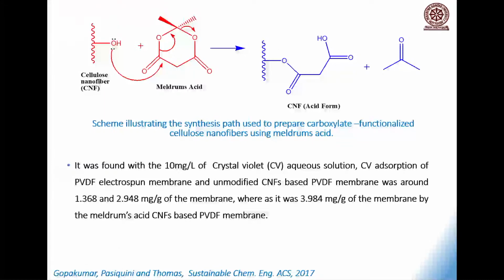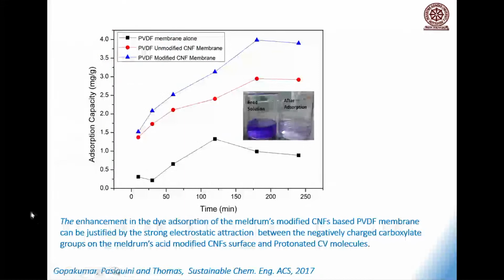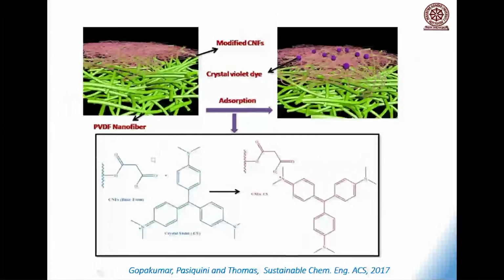And again, we had a collaborator from Brazil, a very brilliant organic chemist. And see what we have done. See, this is the removal of crystal violet from the water we received from the company. Look at, if you use a commercial filter, the adsorption capacity of the dye is something like this as a function of time. If you coat the commercial filter with nanocellulose, look at, the adsorption capacity is increased. And if you coat with chemically modified nanocellulose with the COO minus group, the adsorption capacity is something like 4 milligram per gram. So we could really make the commercial filters pretty efficient. And you might see what is the reason for that. See, this is the chemically modified nanocellulose. This is a structure of crystal violet.